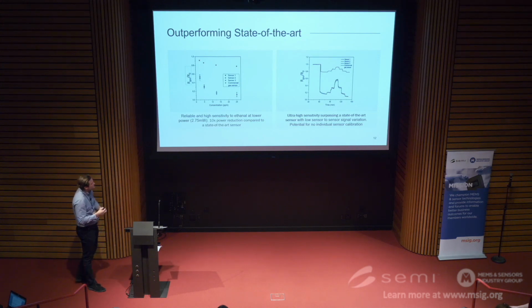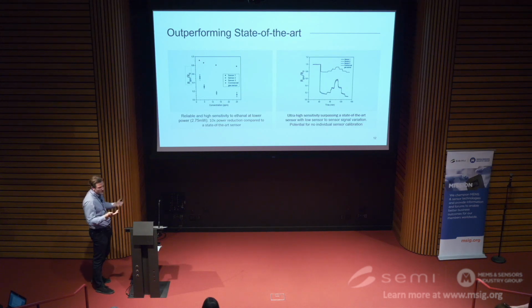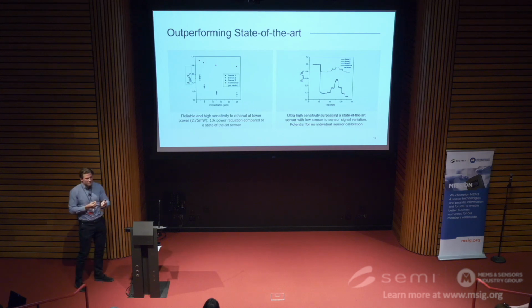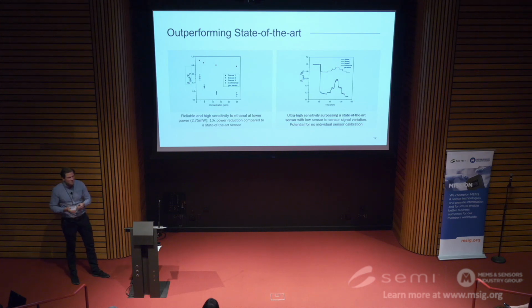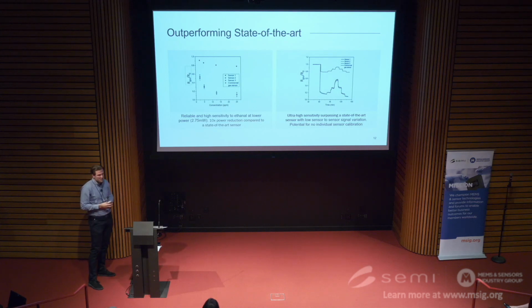On the right side, we can see that the sensitivity is surpassing the state-of-the-art sensor, because as we're miniaturizing, you would typically have less material. But as we can build up structures with higher aspect ratio, we still get a lot of material to perform the gas sensing. Another thing is that we see very low sensor-to-sensor variation, which hopefully requires less calibration in the future, which saves costs for the end user. So this is one of the examples of what we think MPD can enable, not only for the MEMS community, but for the semiconductor community.